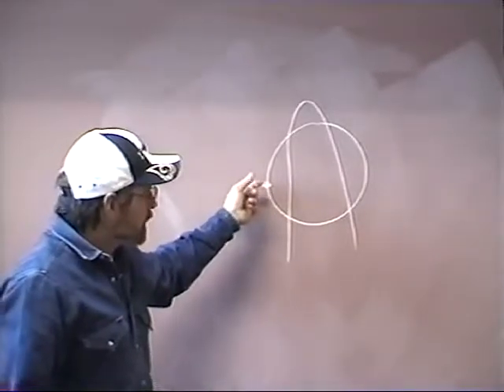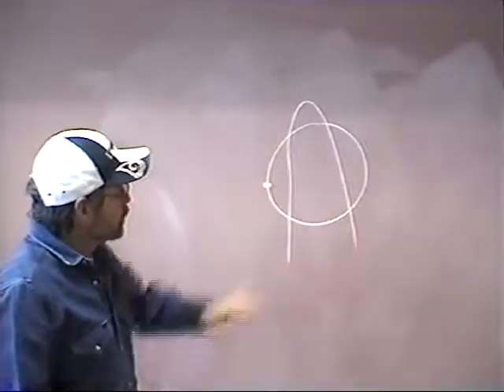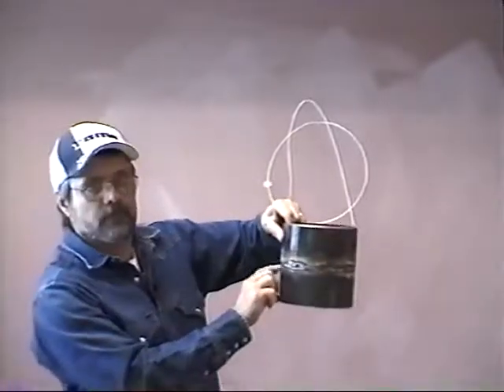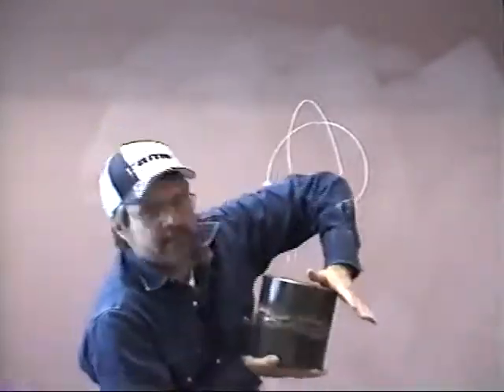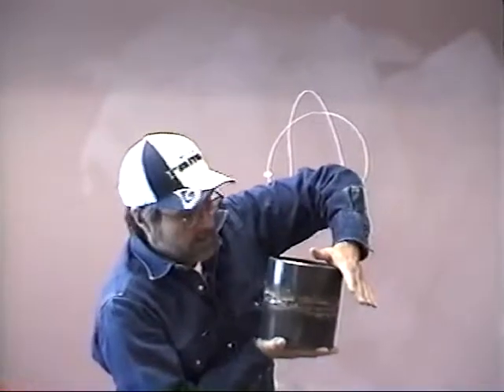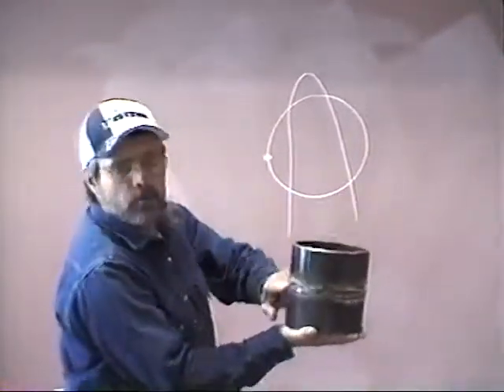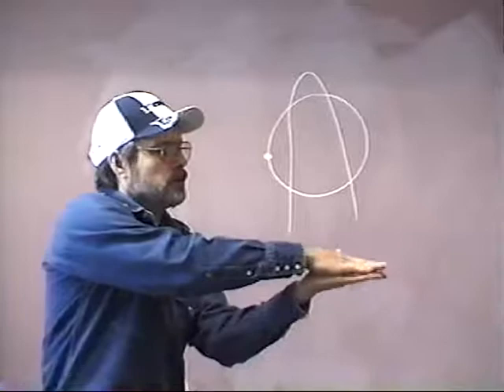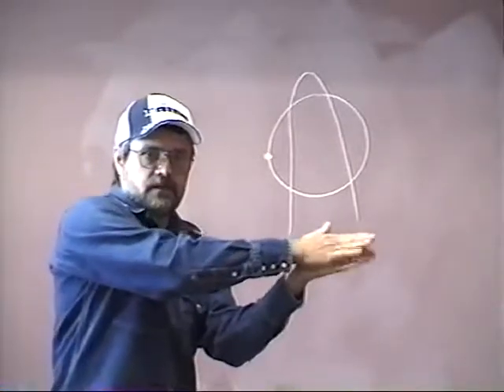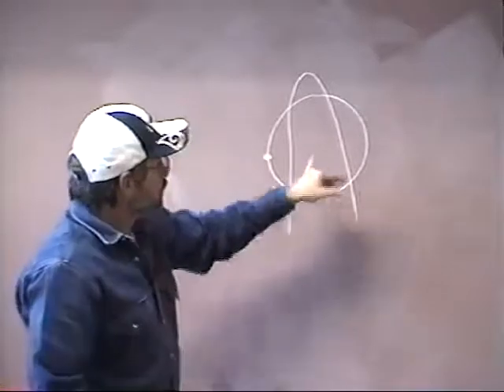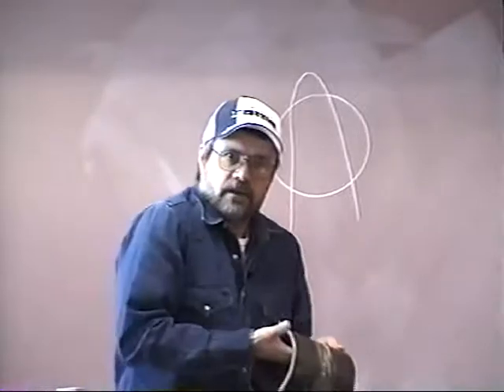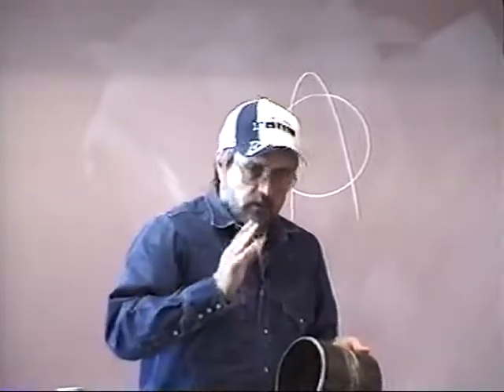As soon as you tie those two coupons together, you're going to reach over here on the other side and press down on it. So I've made my tack here, and I'm going to reach over here and press down on that table and squeeze it down. The reason I'm doing that is to keep this from pulling up as that little tack shrinks. Not only will it pull up this way during that shrinkage process, but it can also shift side to side. So you want to check before you put any other tacks in. Reach down inside that pipe and feel the inside diameter again. Did it pull itself out of alignment? You want to double check that before you ever put that second tack in.